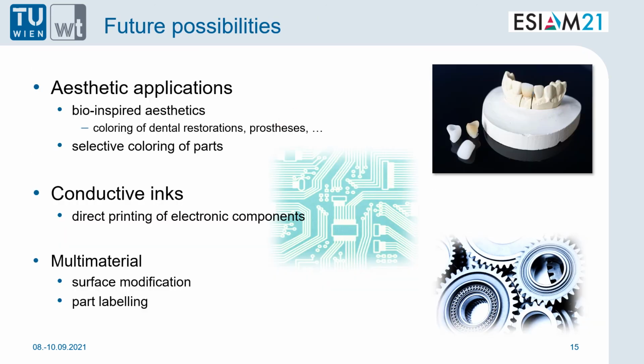With this combined printing system of Cubicure hot lithography and inkjet technology, we now have a powerful tool to print not only colorful parts with good mechanical properties, but very many of them at once. This technology opens up new possibilities for future implementations. Coloring parts for aesthetic reasons is only one apparent application. With the combination of high-resolution printing and selective modification, we can insert more information into a part, for example by marking it during printing or altering the mechanical properties in specific areas. Even introducing conductive inks can be thought of.